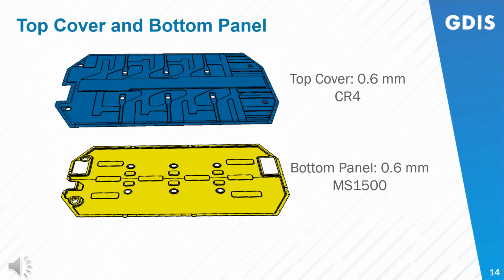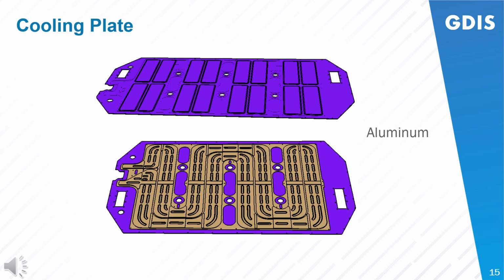As indicated earlier, both the top cover and the bottom protective plate were converted from SMC to steel. The top cover was converted to 0.6 millimeter CR4, and the bottom protective panel, which is the shield, actually is 0.6 millimeter martensitic 1500. Finally, the aluminum cooling plate, which again is consisting of two discrete parts, the top and the bottom being aluminum, has not been converted and is carried over as mentioned earlier.